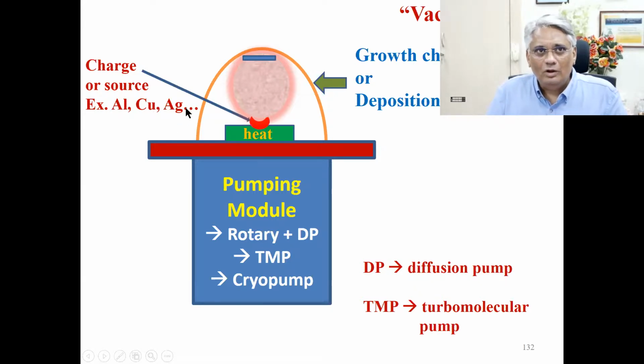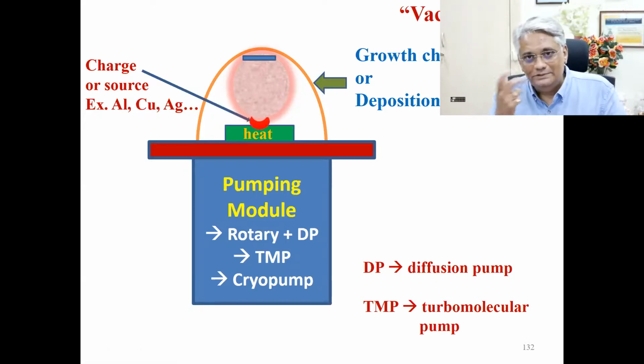That's why I said if you have copper, aluminum, silver, gold, especially these three elements, if you do not remove the air molecules before you start heating it up, what happens? Because everything is at the atomic level, you atomize it, you melt the element, and the vapor is rising. In that process, it can also react with the gas molecules inside the chamber, right? So if air is present, the oxygen and air molecules can react with these elements, and you see the formation of aluminum oxide, copper oxide, and silver oxide. So you're not getting a metallic film, but you get the metal oxide film.